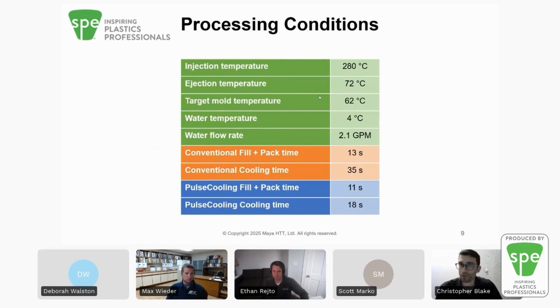And here's a quick overview of the processing conditions. So the melt temperature or injection temperature is 280 degrees Celsius. The ejection temperature as recommended or identified by CITO was 72 degrees Celsius. The resin manufacturer recommends a target mold temperature of 62 degrees Celsius, but interestingly enough, the water that is flowing through this mold is actually at 4 degrees Celsius. Max will allude to why that is the case later on in the presentation. And we have a water flow rate of 2.1 gallons per minute.